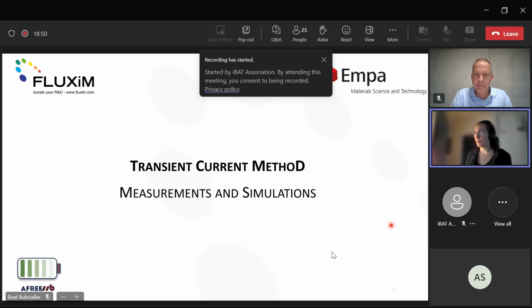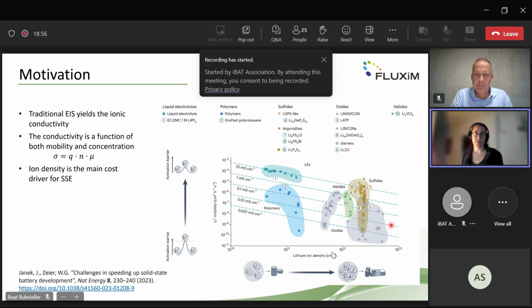This was a collaboration with EMPA. Why is this interesting? As Beat also mentioned, you usually have electrical impedance spectroscopy that gives you the ionic conductivity. And this ionic conductivity is a product of mobility and concentration of ionic charge carriers. It would be interesting, from a material point of view, to separate these 2 quantities. But also, as you can see in this sketch here, because the main cost driver for solid state electrolytes is rather the ion density and not the mobility. So you can achieve a high conductivity through enhancing the mobility